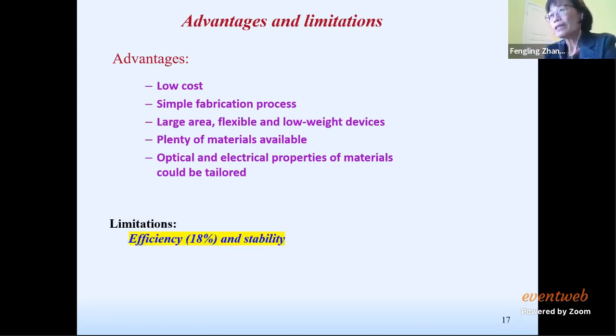So the limitation, as I showed before, is the efficiency, which if compared with inorganic material is still lower, but 18% actually is quite high. Then one thing I would like to point out is 18% is on small area, less than 1 square centimeter. It's very small area. If we upscale or we need a big area device, then the efficiency will be much lower than this number. The other issue is stability, because for the application, stability is a key issue.